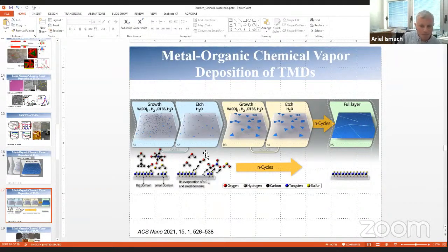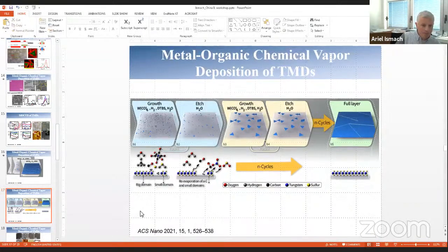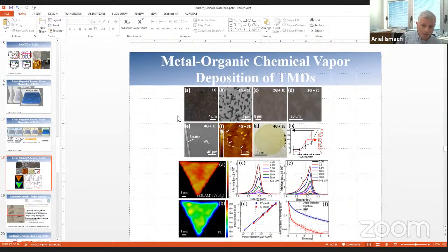So this is the basic idea of the growth and etch methodology. And again, you can see here, for example, images of different sequences. We're not going to get into details, but different sequences showing the increase in the domain size, the brighter triangles or isolated domains. And eventually we can grow single layer wafers using this